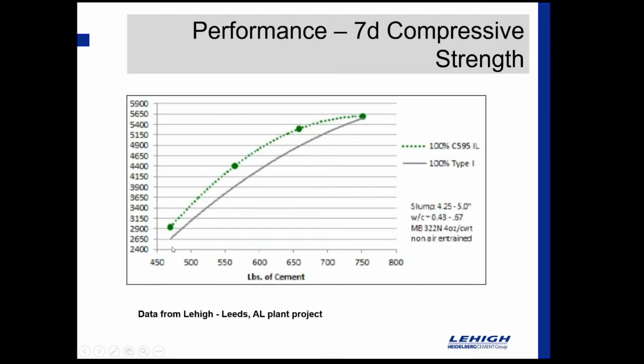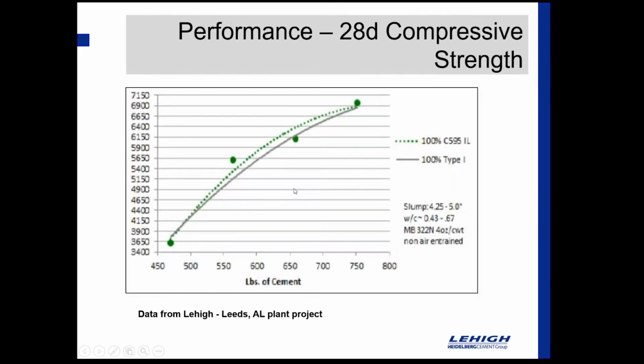And pretty much true to what the industry literature says, you can scour, PCA has all kinds of information about PLC and their performance. Typically what you're going to find is that there's a bump in the early strengths, and those strengths will tend to equate with more of the type 1 strengths at 7 and 28 days. And that's kind of what they saw when they did the Leeds project. You can see the green line here is the Type IL data, just a bit stronger at equivalent cement rates in their trial batches. And then at 28 days, you can see that tends to close up a bit, but again, good performance from the Type IL cement.